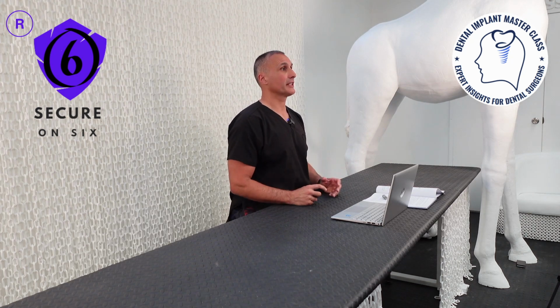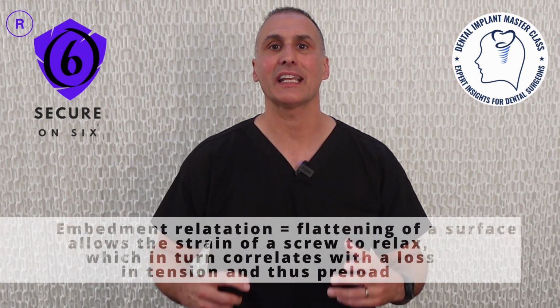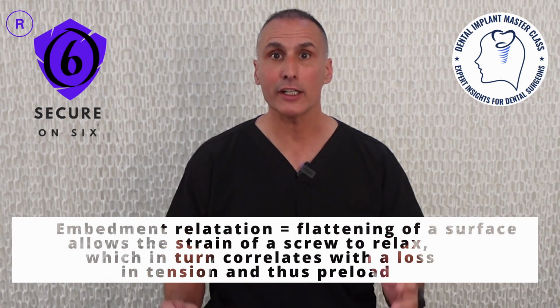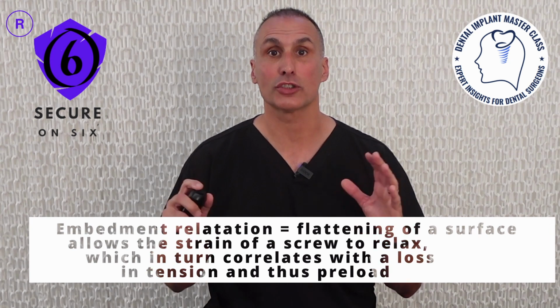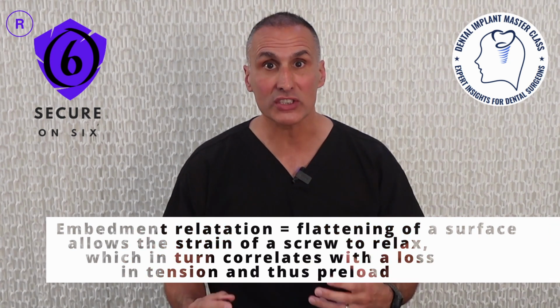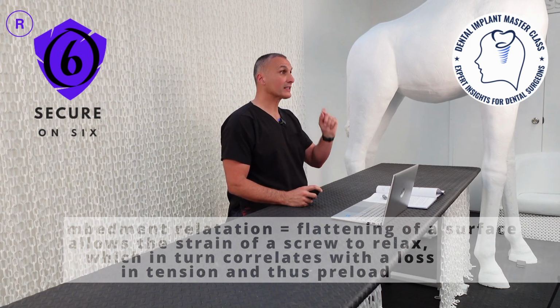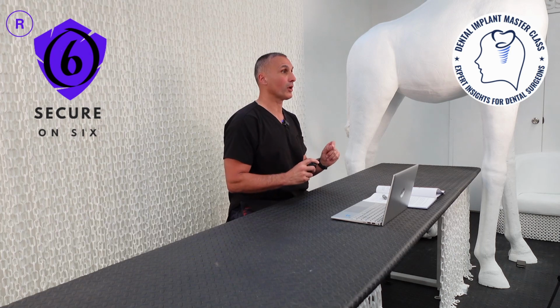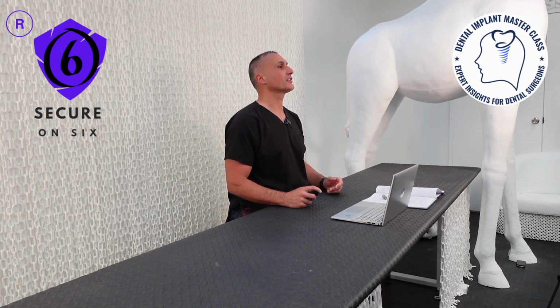It has been hypothesized that up to 10% of the initial preload may be lost due to the settling effect. Thread friction is highest during the first tightening and loosening of the screw, and after repeated cycles, friction decreases. As a result, the torque required to remove a screw is always less than the torque used during the initial placement. This phenomenon is known as embedment relaxation, where the flattening of the surfaces allows the screw's strain to relax, leading to a loss in tension and preload. Consequently, some experts suggest tightening the implant abutment joint periodically after initial screw insertion.